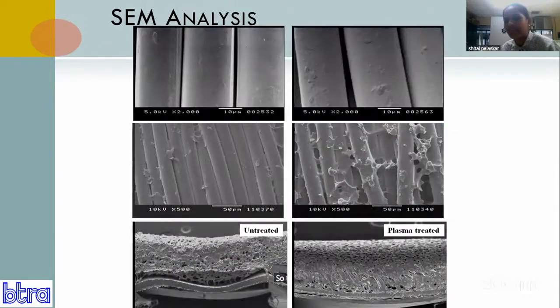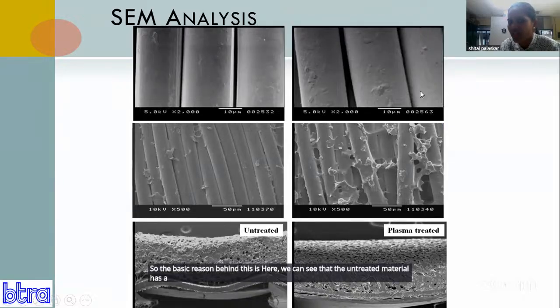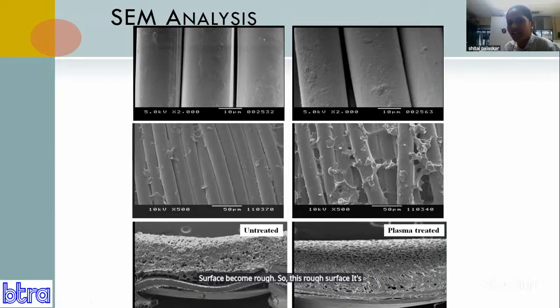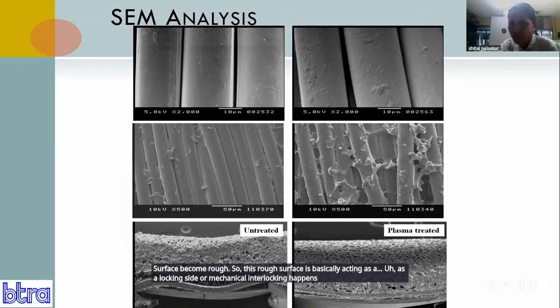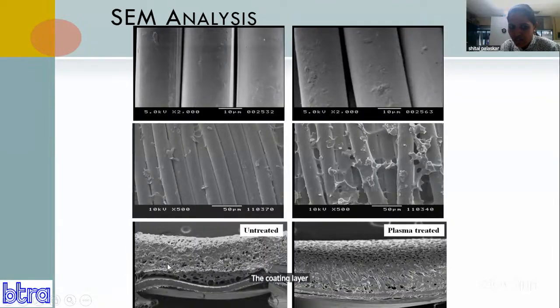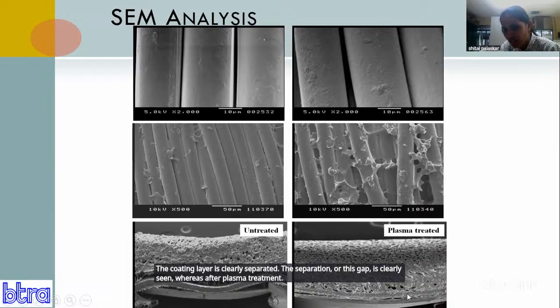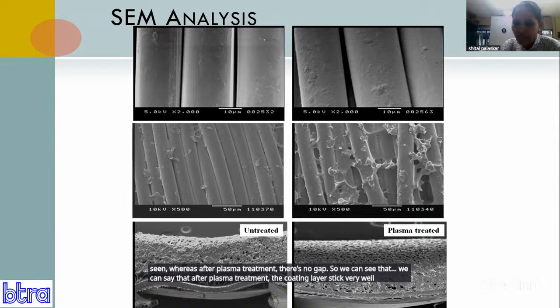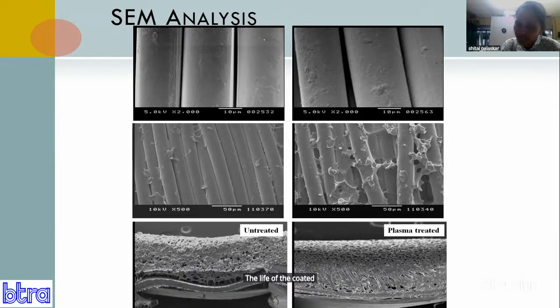The basic reason behind this is that the untreated material has a plain surface, whereas after plasma treatment, the surface becomes rough. This rough surface basically acts as a locking site, so mechanical interlocking happens with this rough surface. Here we can see that for the untreated, the coating layer is clearly separated. The separation or this gap is clearly seen, whereas after plasma treatment, there is no gap. So we can say that after plasma treatment, the coating layers stick very well to the base material, which is the reason the life of the coated material gets increased.